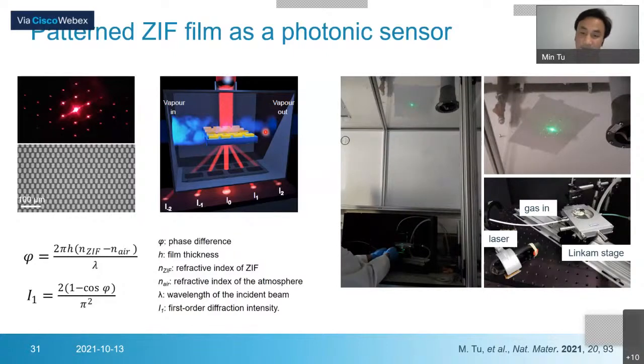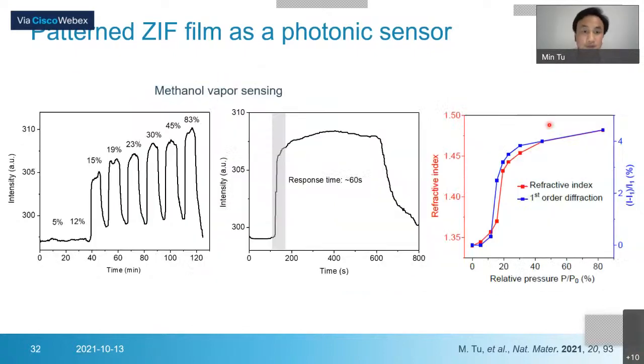So we developed a very simple sensing test system. We have a laser shining on our MOF pattern. Then we can see the diffraction spots. By monitoring the intensity change of the diffraction spots, we can realize the sensing signal transduction. Here is just one example of methanol vapor sensing. We can see it's not completely reversible sensing, and the response is around 1 minute.